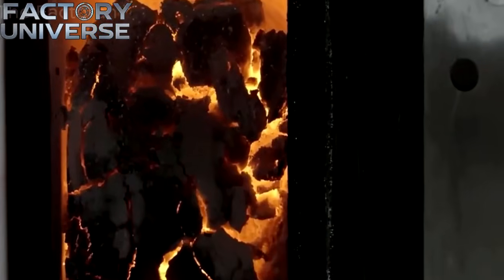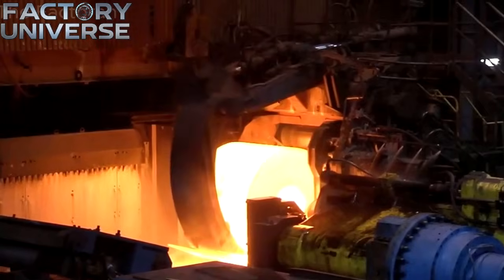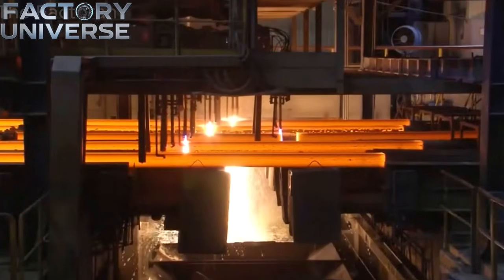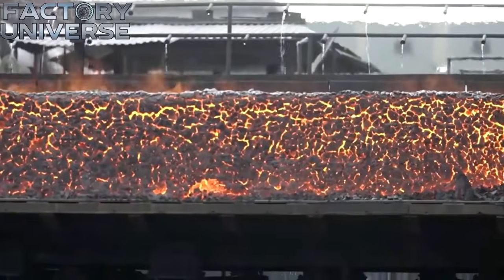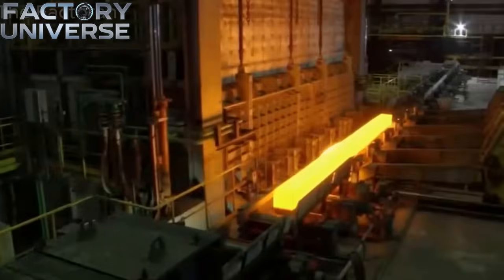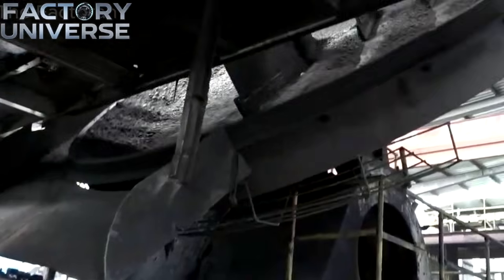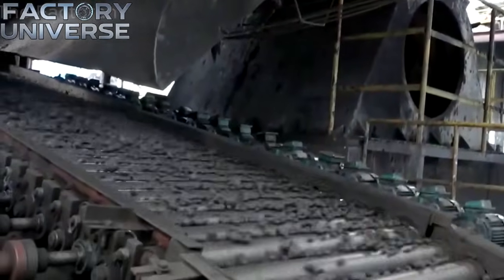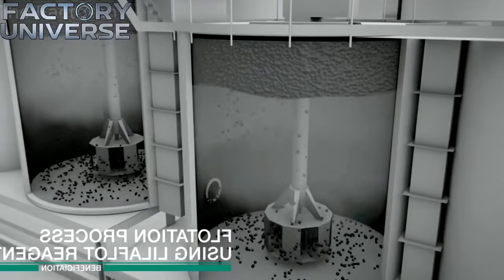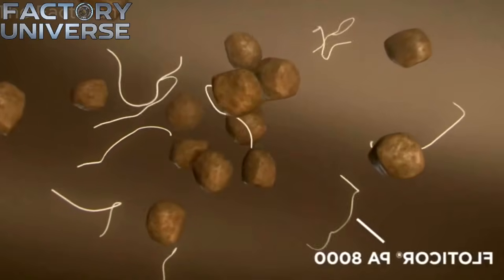Inside, flames shoot from the kiln's mouth, sweeping the entire length and turning the chamber into a blazing river of heat. It gets more complex further on as the thermal treatment begins. Pellets tumble and roll evenly through temperatures ranging from 1,200 to 1,350 degrees as the drum rotates. This constant motion ensures each pellet is baked uniformly from core to surface, eliminating weak spots or cracks.